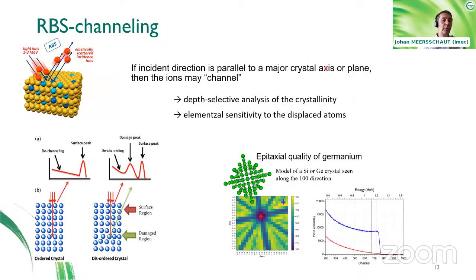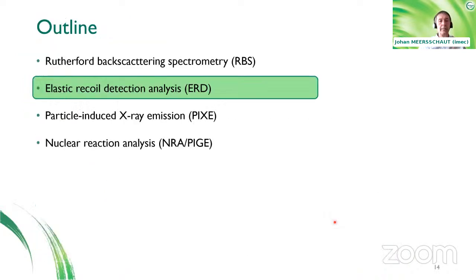A last technique which I would like to mention with respect to Rutherford backscattering is channeling. So this is a technique where we are aligning the sample with the crystalline axis along the incoming or exiting axis of impingement of the ions, and it allows us to determine the crystalline axis of the sample under investigation. Now, if you would have a little bit of oxygen on the surface of such a sample, it would be superimposed onto the very intense signal which is coming from the substrate. And this is, you could say, a limitation of Rutherford backscattering spectrometry.